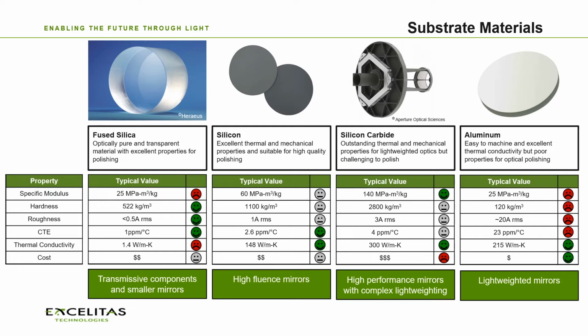Our second material is silicon. Silicon is a general purpose material that is used when high optical polishing quality is required, but also thermal conductivity is key. It forms some sort of a middle ground between some of the other materials. It doesn't necessarily excel in any one area, but it has a nice balance of the specific modulus, thermal expansion coefficient, thermal conductivity, and cost, which are key considerations.